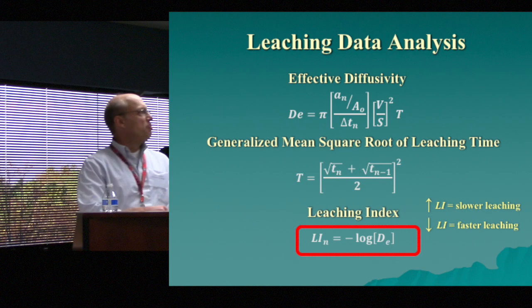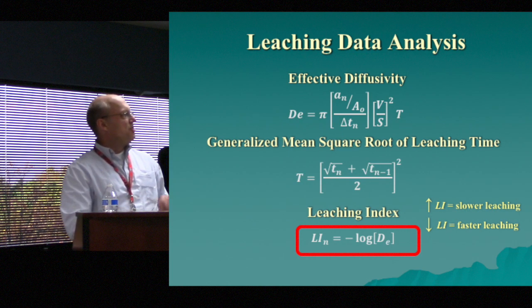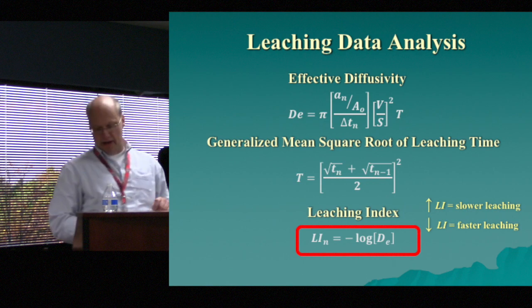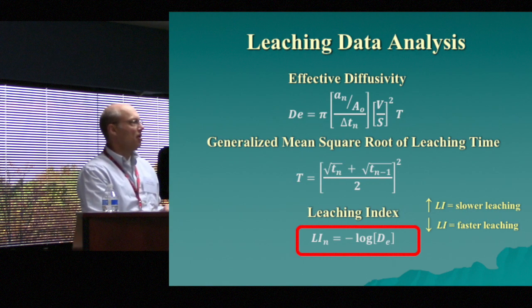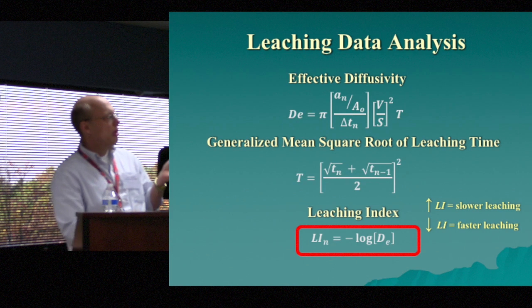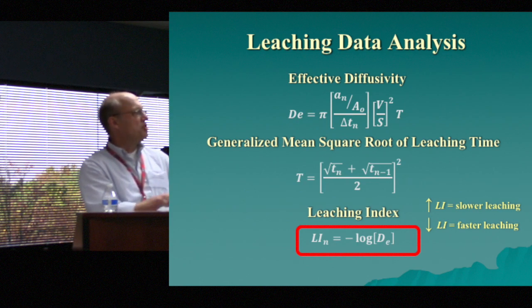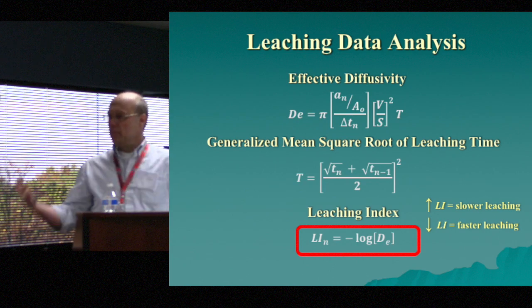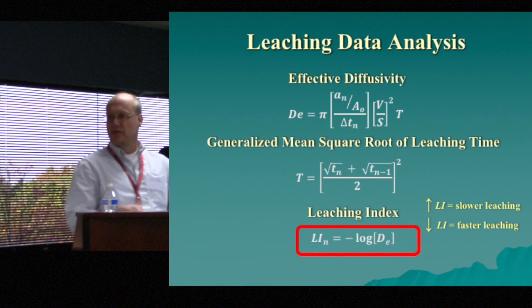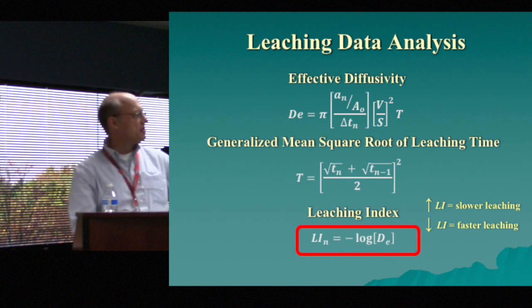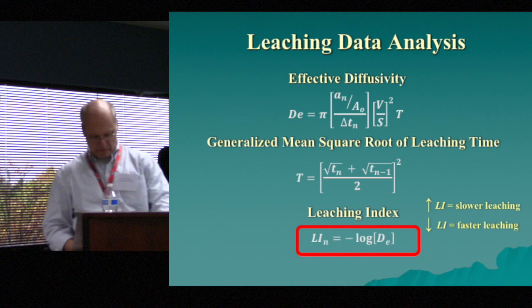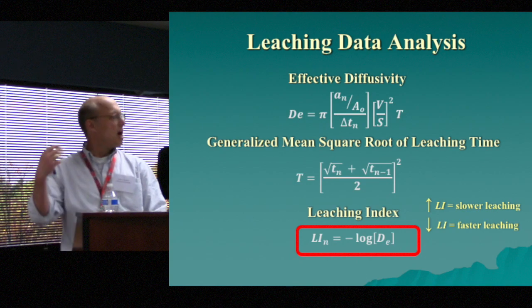And what you do is you use the effective diffusivity to calculate a leaching index, and that is the negative log of the effective diffusivity. And what that means is that if it's leaching slower, coming out, it's more immobilized within the material, then that leaching index goes up. If it's actually leaching faster, then the leaching index goes down. Next slide.